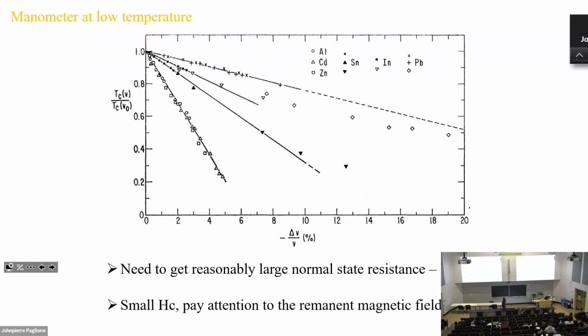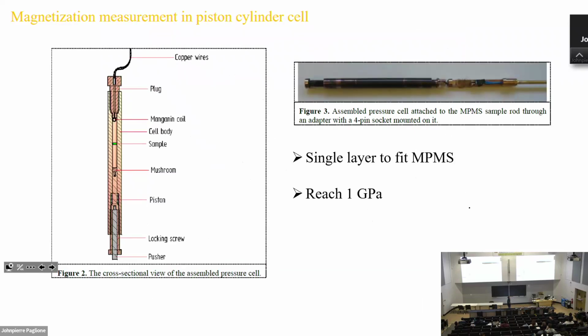Okay. All right. So up to this point, hopefully we know how to use a pressure cell and do resistance measurements. But this type of cell is actually very versatile. You can do, for example, magnetization measurements, and you can put it in a PPMS or MPMS for SQUID measurements. And there, the sample chamber is very small, so the idea is you only use one layer of cell, and so the pressure cannot go very high, about 1 GPa.